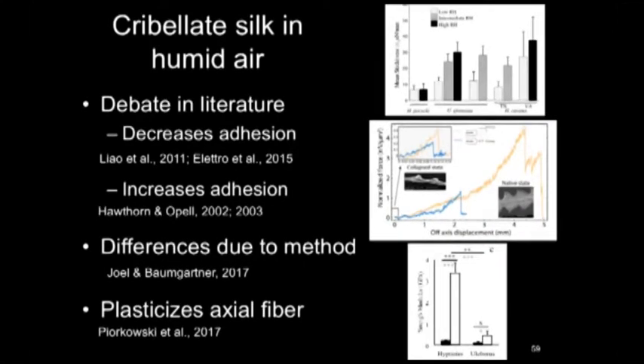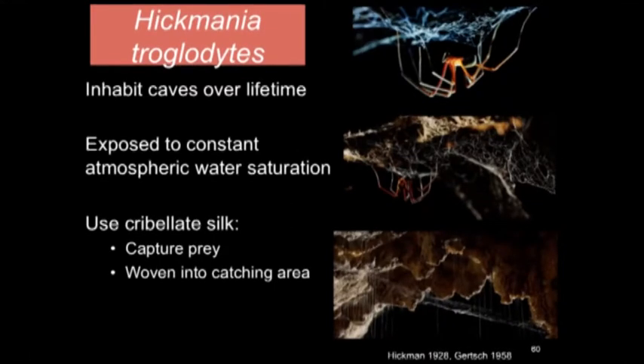So this brings us back to Hickmania. As I said, they inhabit these caves and these wet environments over the course of their entire life, which means that they're exposed to constant atmospheric water saturation, meaning that they're constantly exposed to wet conditions and they need to be able to catch prey in these wet conditions. So we thought, well, it's unlikely then that their silk should be collapsed or non-functional because they live in these conditions constantly. They use this cribellate silk again in their webs to catch prey, and this is really quite important to them because their metabolisms are slow and the food resources are low, they can't miss out on opportunities to catch prey. Their silk needs to perform well.